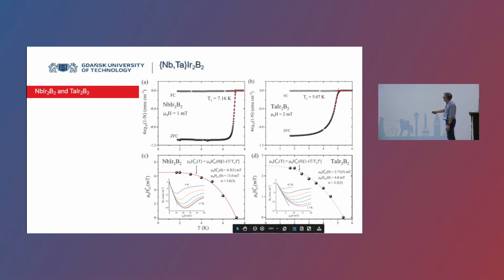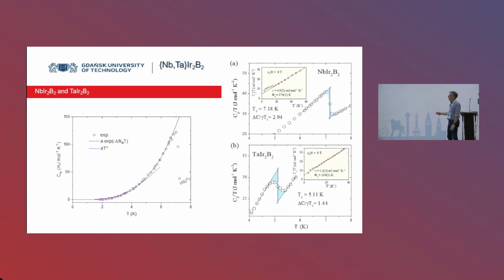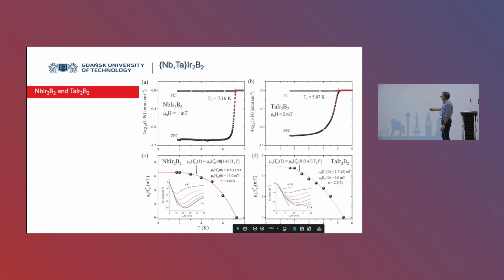And what is striking here is when you plot the lower critical field as a function of temperature, in this fit, usually you just take n equal to 2. But in this case, we must have close to 4. It's 3.8. For tantalum iridium 2 boron 2, the power law is 2.5, so it's close to 2, but in this case it is almost 4. We don't know what the reason for that is. Actually, we observed such a high value of n in only 2 cases, and that's one of them.